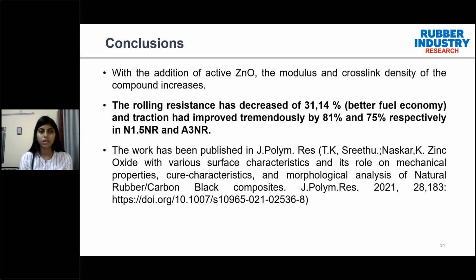So in conclusion, we say that with the addition of active zinc oxide and nano zinc oxide, the modulus and the cross-link density of the compound increased. And we already explained that the rolling resistance has decreased by 31 and 14%, which actually gives a better fuel economy, and the traction improved by 81 and 75% for the batches of N1.5 and A3NR compounds.